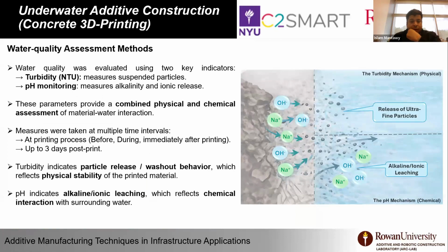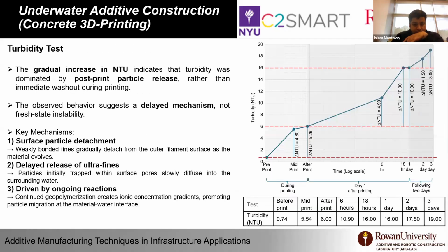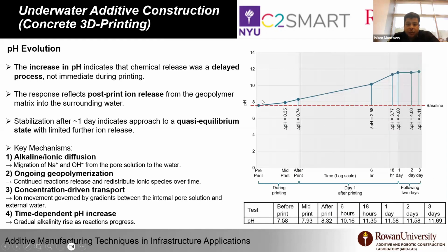We also thought about how we can impact the water by leaching of the materials, especially the ions, during the print. So we did some water quality assessment to measure turbidity and pH, especially since this material is alkaline based. We did a lot of work. It's not going to be a focus of this presentation, but this shows the impact of fresh printing of concrete underwater, especially geopolymer, on turbidity, which is basically the particle suspension and release, and the pH value of the water you print with. It's still ongoing and nothing really scalable to implementation, but it's emerging technology within emerging technology, as I mentioned.